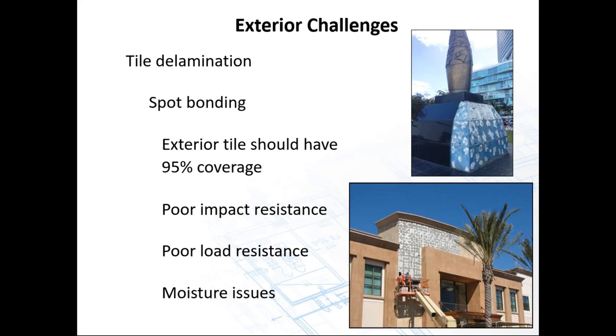Exterior tile should have, if you remember one thing today, remember this: 95% coverage. It's a very critical part of the application. Also, when you get into spot bonding, you'll end up with a poor impact resistance. If you're around an area where traffic might be up against it, or a lot of people are coming across it, you have a poor load resistance, and then of course with moisture issues that we just mentioned.